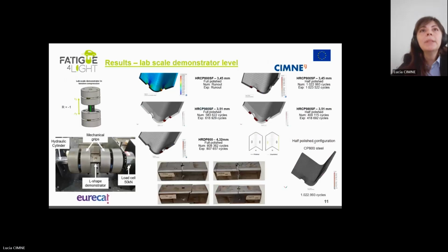approach. Okay. Now, second year of the project, we wanted to complicate the problem a little bit more, so go to higher scales. And we devoted some time for this lab scale demonstrator level. And we've chosen a demonstrator, which is this L-shaped profile, which has some holes, which are representative of, well, typical geometry that you would find, obviously including some holes on chassis components. We've dedicated some time to analyzing different behaviors in terms of polished component or unpolished component. Okay, so seeing a little bit what was the effect of these surface treating techniques.